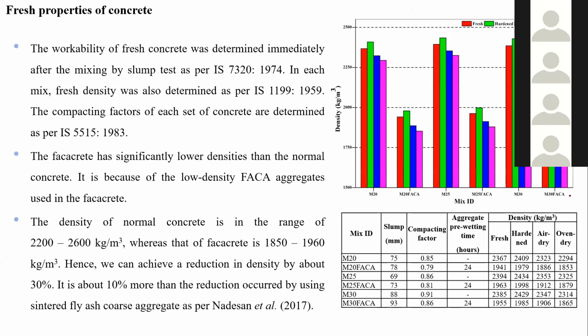That is the FACA. So these are some fresh properties, for example slump, compaction factor and all those things. More or less it looks like conventional concrete. For example, I can take the density of M20 with the FACA. This density is less when compared to conventional concrete, whether fresh, hardened, or oven-dried density. Because there is only fly ash inside the aggregate, the density is much less when compared to conventional aggregate. So that is a problem.